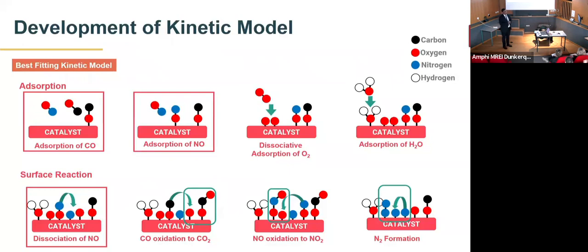Yes. Okay. So do you think applying a kinetic model can be a predictive tool to help with the modification of the catalyst composition? The problem with the kinetic model is that the model parameters change with the material composition. Yes. So in fact, you can say, okay, my model says that my problem is finally to activate the dissociation of NO. So I will modify my catalyst according to this conclusion, adopting an agent or method to favor the dissociation of NO.